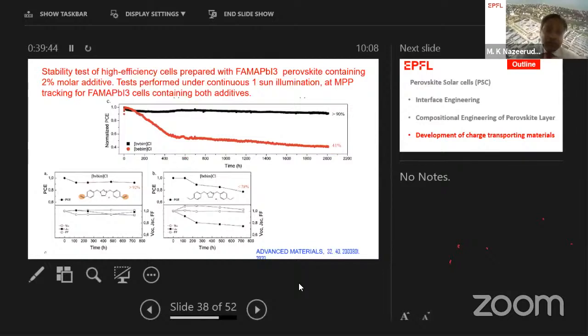On the left side, we have a polymerizable ionic liquid. In one cell, we use the polymerizable ionic liquid, and in another cell, we have used an unpolymerizable ionic liquid. The stability data are shown here. With the polymerizable ionic liquid, after 2000 hours, the initial efficiency remained at 90%. However, without any polymerizable groups, the power conversion efficiency decreased to 40% of its initial efficiency.